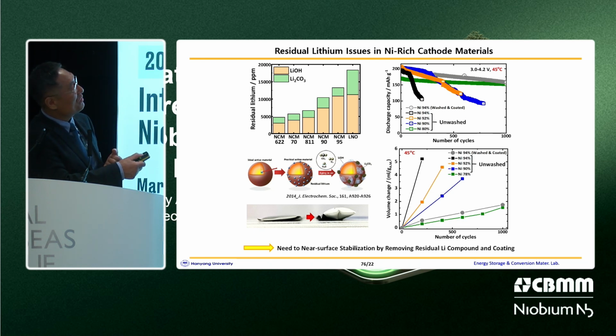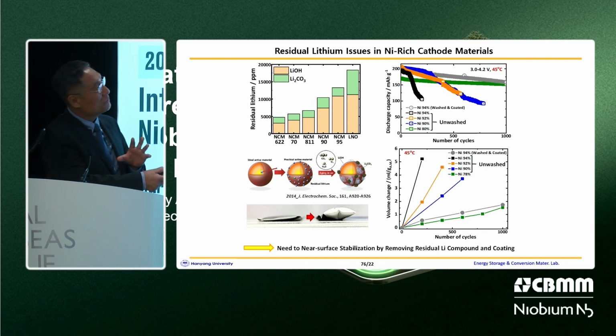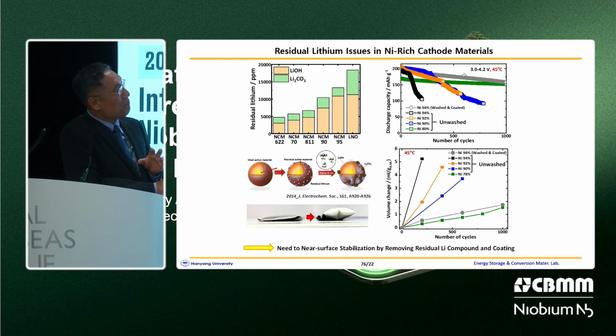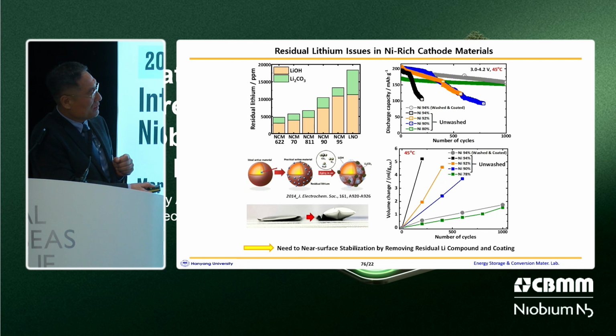And as you can see here, the residual lithium amount increases with increasing nickel content, especially nickel content of more than 90%. And as you can see here, the NCM 811 cathode material stably cycles up to 1,000 cycles without a washing process. However, the nickel-rich cathode material with nickel content of more than 90% shows severe capacity fading. And also this is the gas evolution as a function of cycle number, and gas generated from the decomposition of the residual lithium leads to cell swelling, which results in poor cycling performance.